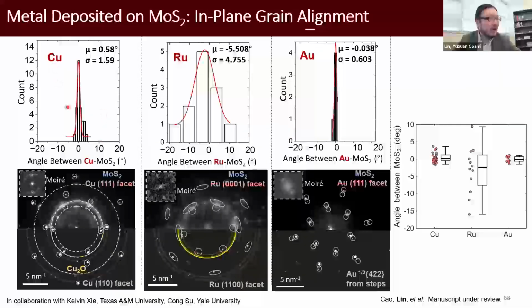So for copper, the dominating facet is 111. They more or less align with the MoS2 crystal. For ruthenium, the distribution is wider, but we also see an alignment trend. For gold, it's the best. It can align very well with the MoS2. So here are the statistics, so we can see the alignment. Without MoS2, the grains are randomly oriented.